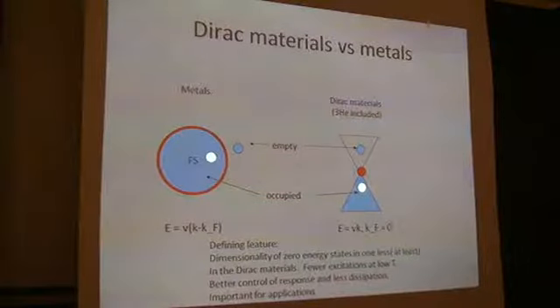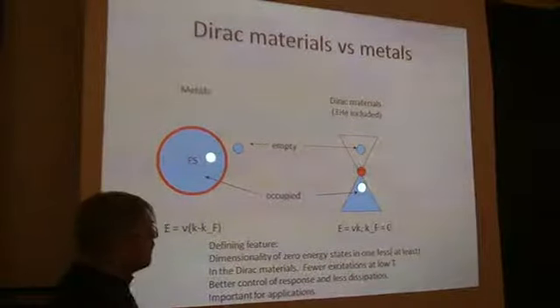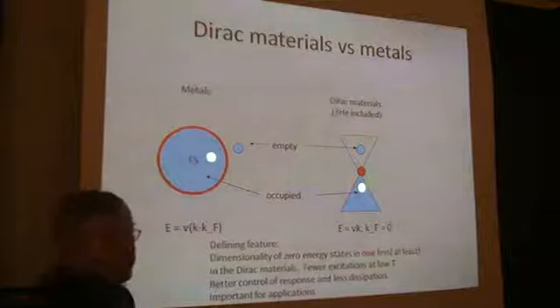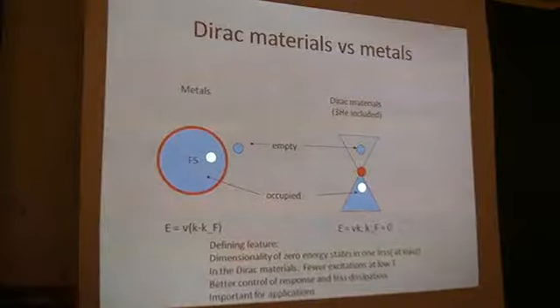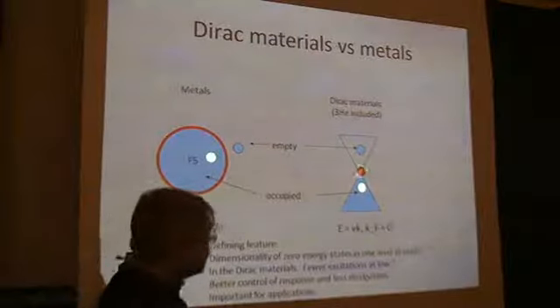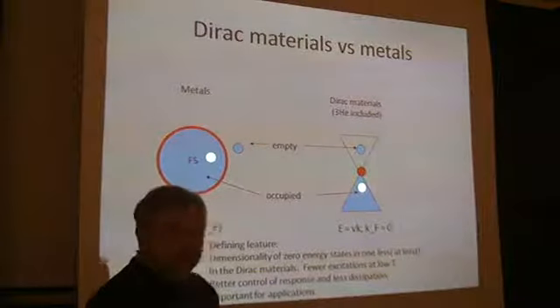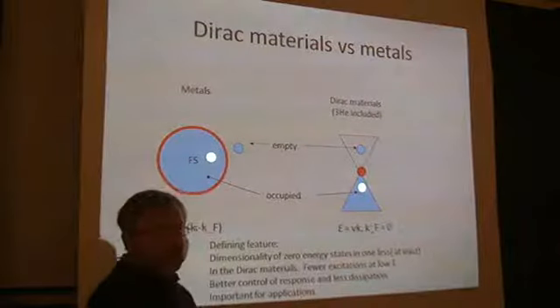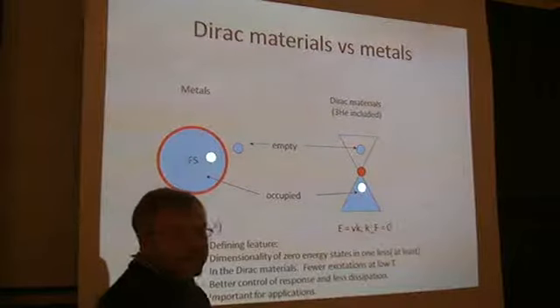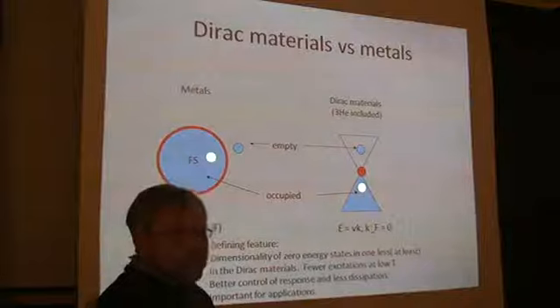It means that there is an additional organizing principle at work, and also additional symmetries that could be at work, at either the level of the band structure or the level of the disordered state, basically allowing this unusual crossing point. Put differently, if I have a crossing point between two bands, typically what happens is that there is an avoided crossing and the gap opens up. And this point is protected only if there is additional symmetry that holds it together. So you can say from the outset that the phase space, or the number of these Dirac materials, will be much smaller and fewer.